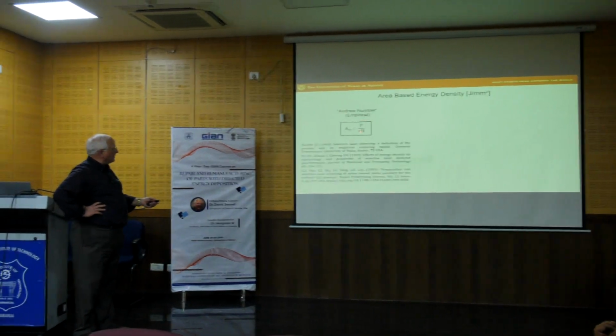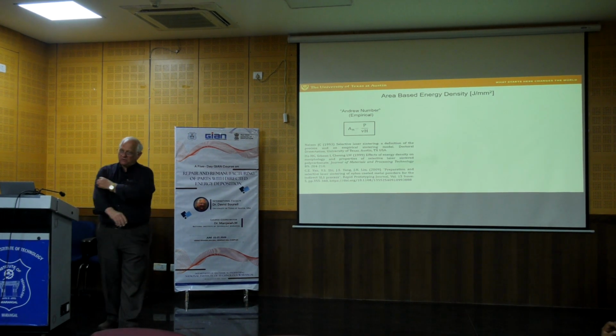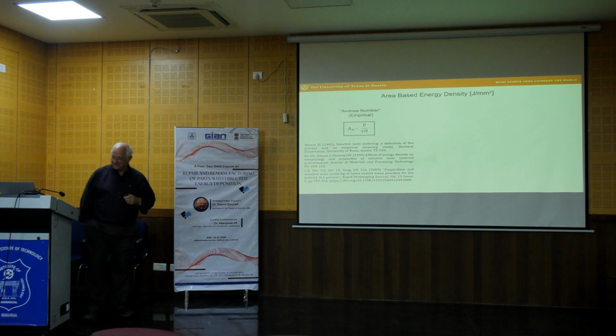divided by the scan speed times the hatch spacing. That was his parameter for energy. And so you can see that the difference between this and the first energy term is that the layer thickness is missing, right? So that's the difference.